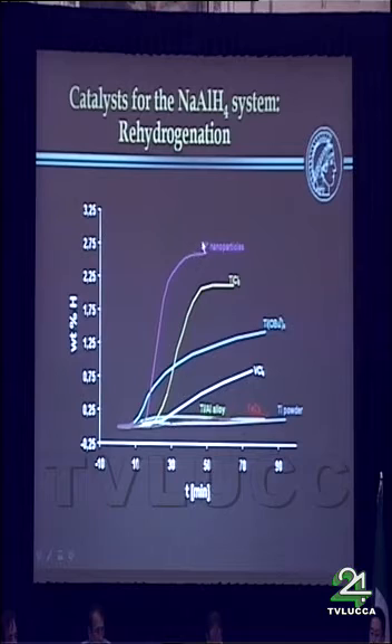The best is the titanium nanoparticles. Titanium trichloride is rather good, and if you directly synthesize, the rate is like the titanium nanoparticle rate, so it depends on the method of synthesis. Alkoxides are certainly not as good, and basically most of the other catalysts which have been investigated are far inferior.